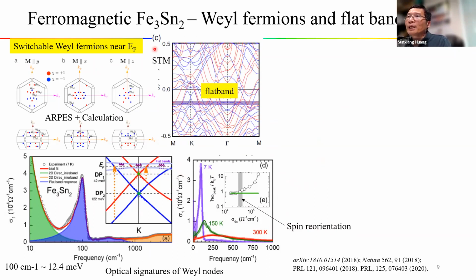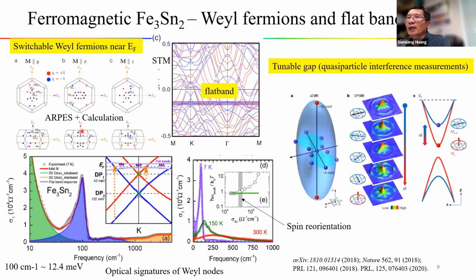The flat band has also been confirmed by the STM measurement, although the flat band is about 200 milli eV below the Fermi energy. Another interesting property in this material is shown by the quasi-particle interference measurement using the STM. So the basic idea is that the aforementioned Dirac gap can also be tuned by the orientation of the magnetization. So this shows that with the magnetization along different directions, the quasi-particle interference pattern is different, indicating the gap value is different. So, in short, these materials, just like the manganese-tin, are another exciting material we should explore.